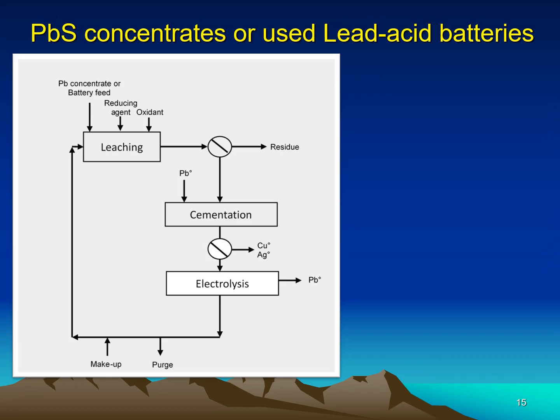We can combine the two major stages in the process, the leaching and the electrolysis, into a flow diagram. After leaching, the inert or non-reacting phases are filtered out. In the case of the concentrate, this would contain other sulfides and non-sulfide phases. In the case of the galena concentrates, we can anticipate that a small amount of silver or copper could be leached,